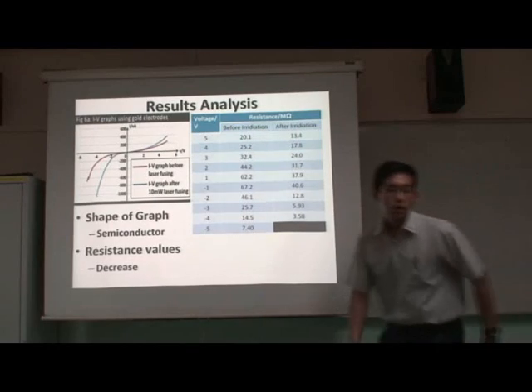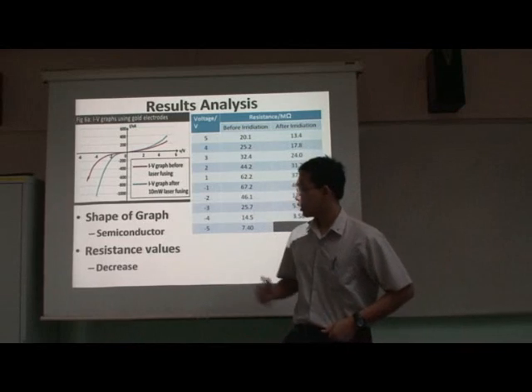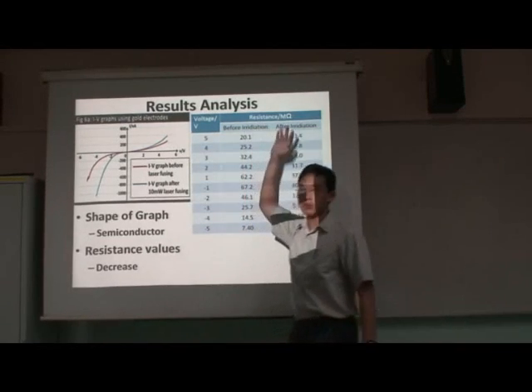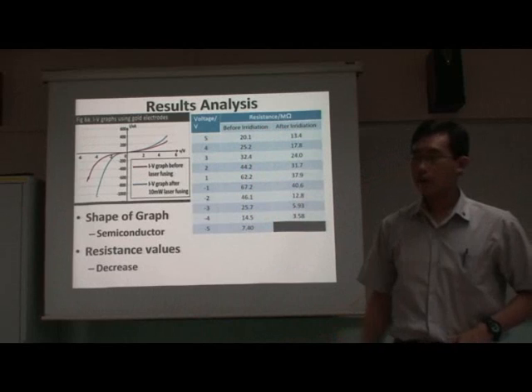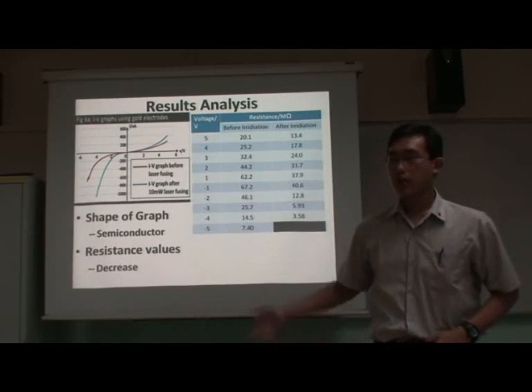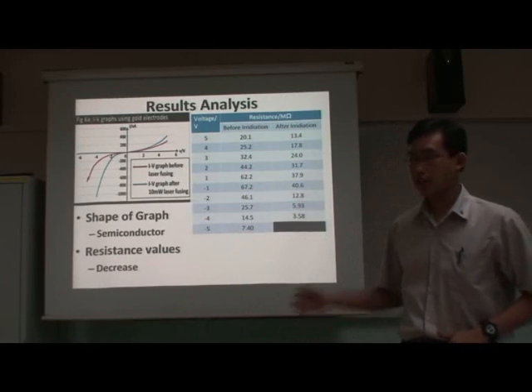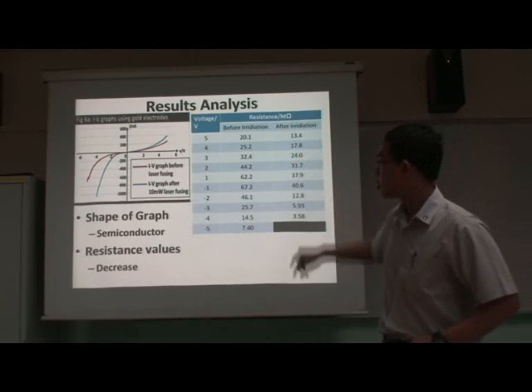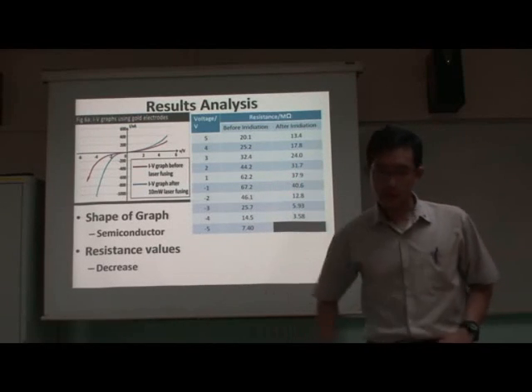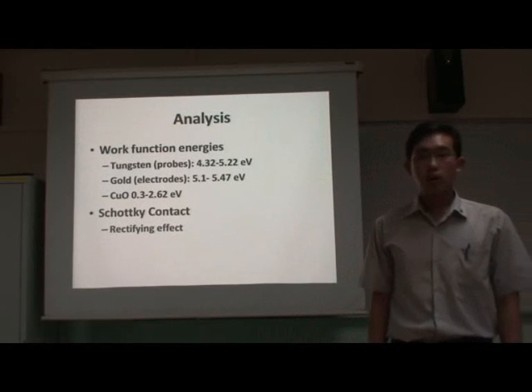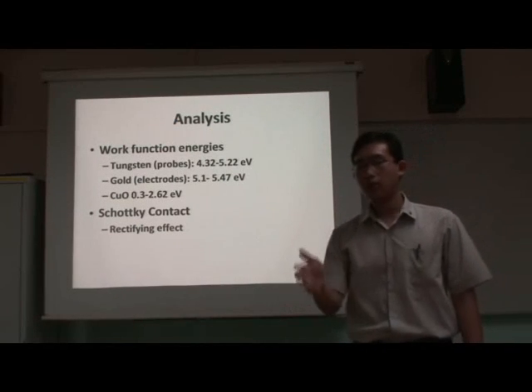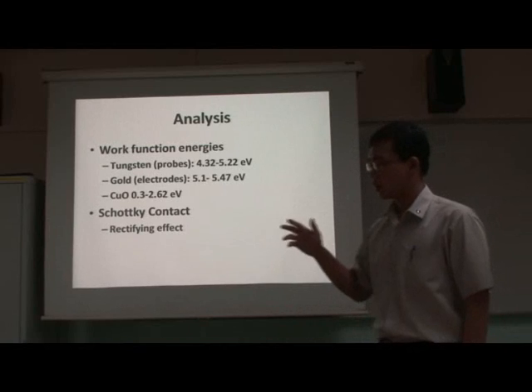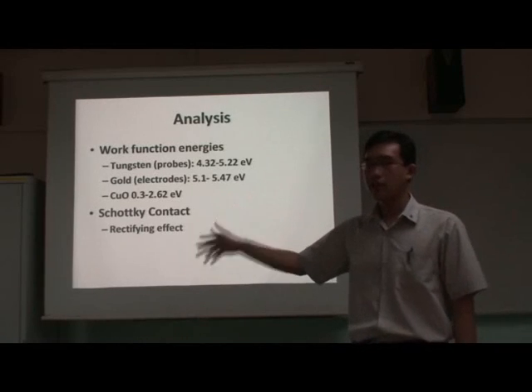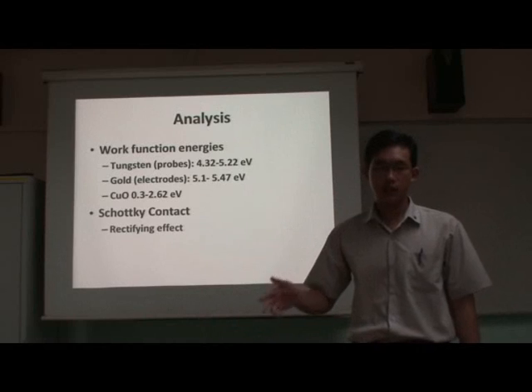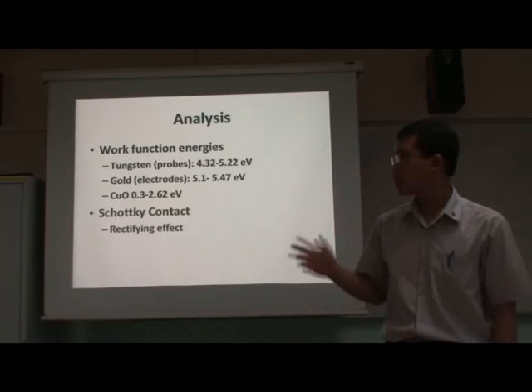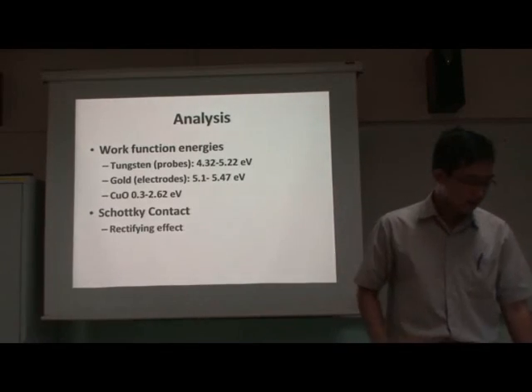Thank you, Benjamin. So after everything, we have obtained a graph and a set of table values. Our graph roughly follows that of a semiconductor, and at several points throughout the graph, you can see that there is a decrease in the resistance from 5 to 1 and from -1 to -5. We could attribute the graph to have such a shape because of the Schottky effect, and this is so because the work function value for copper oxide is relatively much lower than tungsten and gold.